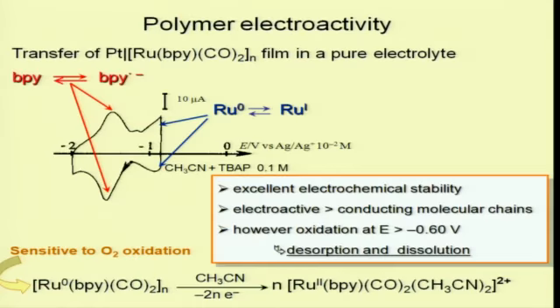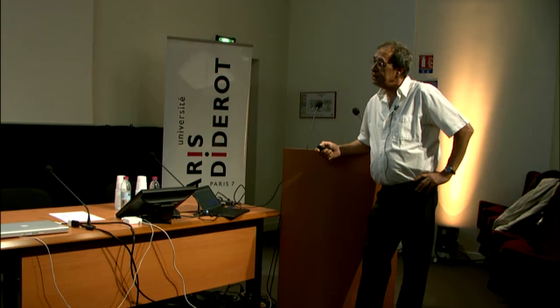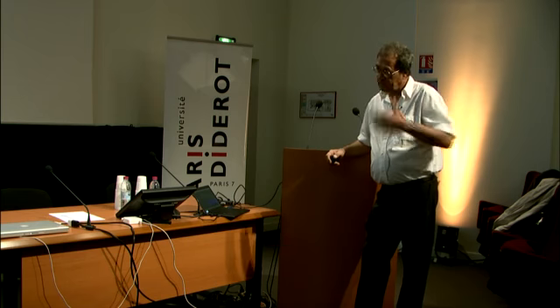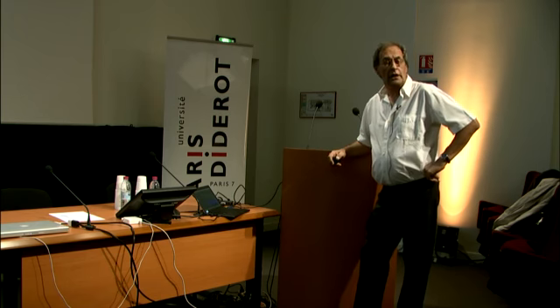Well, as usual, it's very common. If you transfer the film into pure electrolyte, after a while you can observe the electroactivity of the film itself. And as I said, the film is electroactive. That's the rest potential; you start from there, in fact. The film can be reduced. We have demonstrated that later.